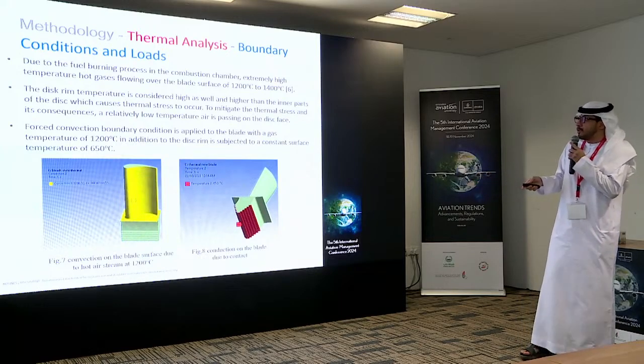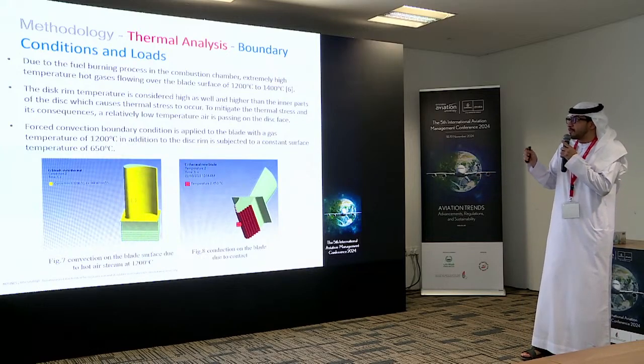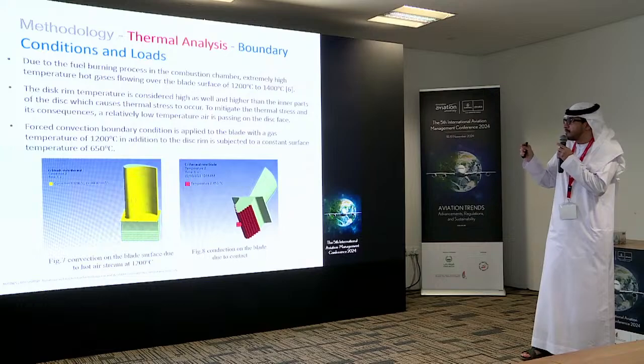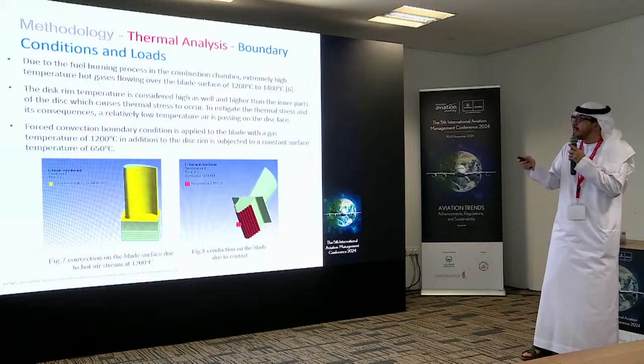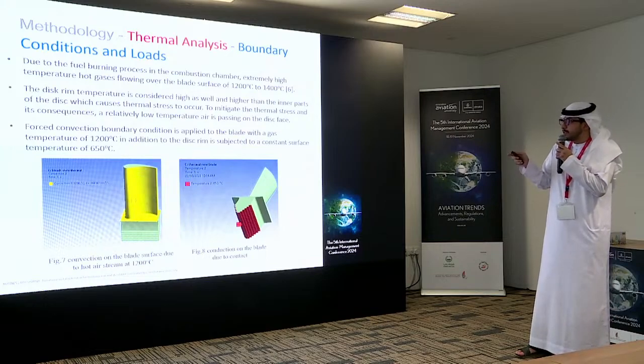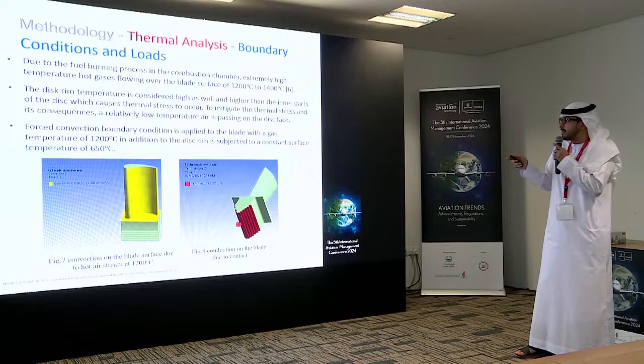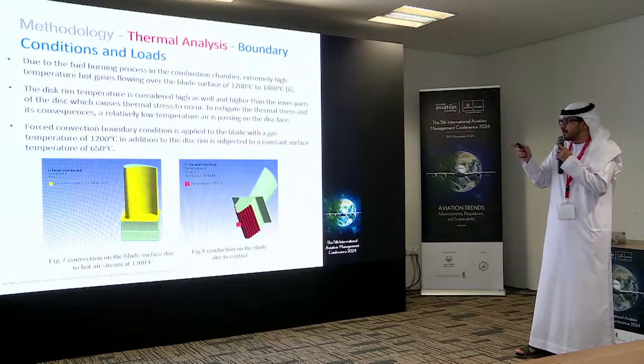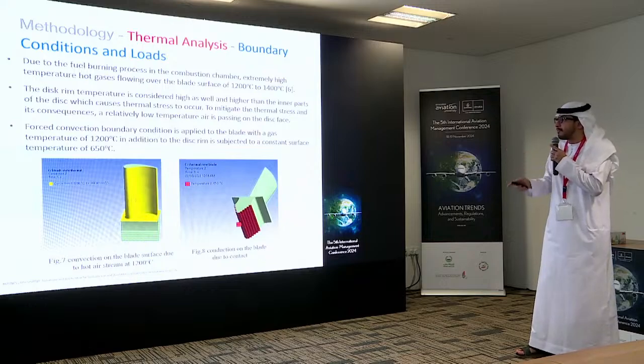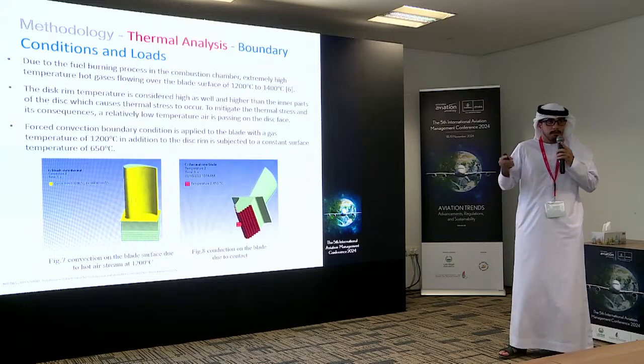The boundary conditions and loads. Due to the fuel burning process in the combustion chamber, extremely high temperature hot gases flow over the blade surface at 1200, as we mentioned before. The disk rim temperature is considered high as well, and higher than the inner parts of the disk, which causes thermal stress to occur. To mitigate the thermal stresses, relatively low temperature air is passed on the disk face, which was extracted from the compressor, as we mentioned.